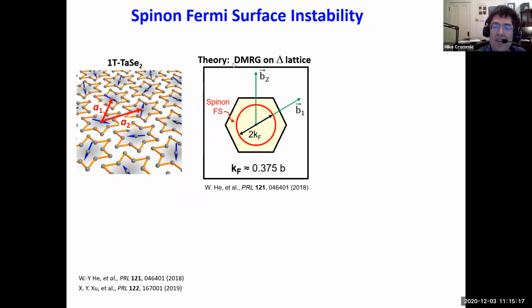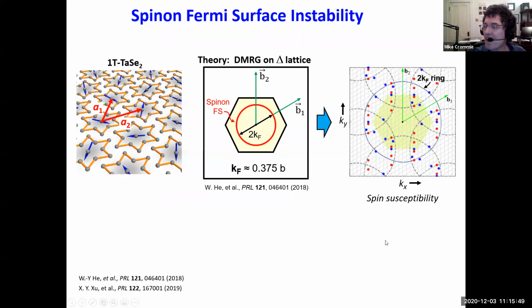And so what they predicted using their DMRG calculations is that indeed this material should be a quantum spin liquid that has a gapless spinon Fermi surface. And they predicted that the Fermi wave vector of that spinon Fermi surface should be 0.375 B, where B is the reciprocal lattice vector of the charge density wave, the main reciprocal lattice vector. And they also predicted something else. They calculated the spin susceptibility of this system using their DMRG, and they calculated that the spin susceptibility should have a peak at 2kF, at wave vectors of 2kF.